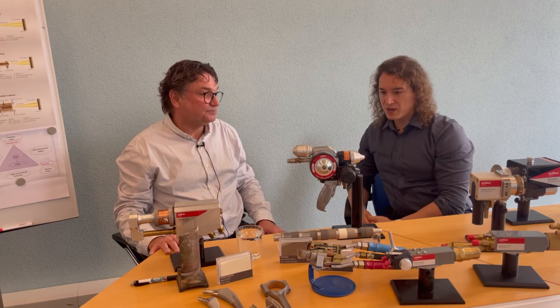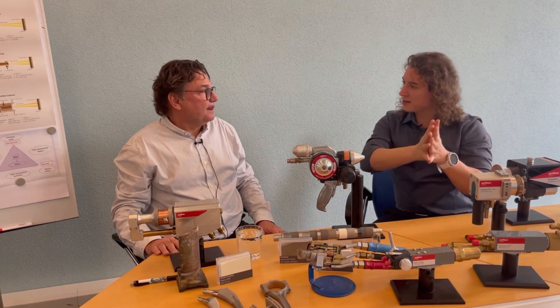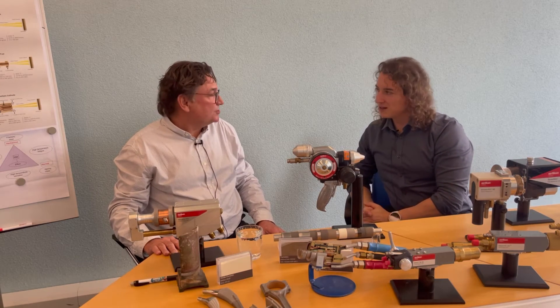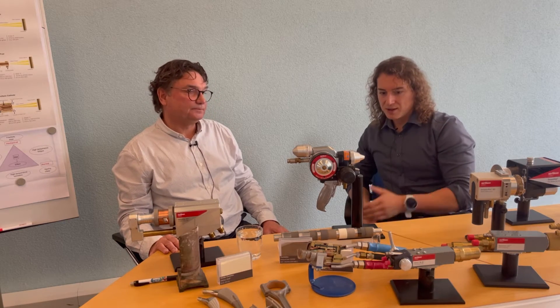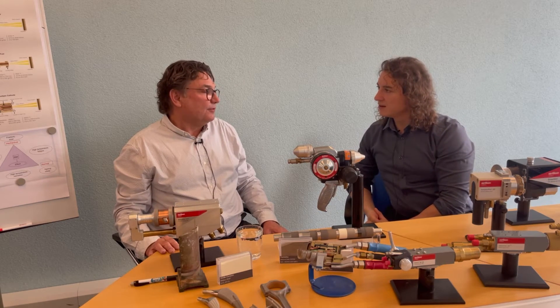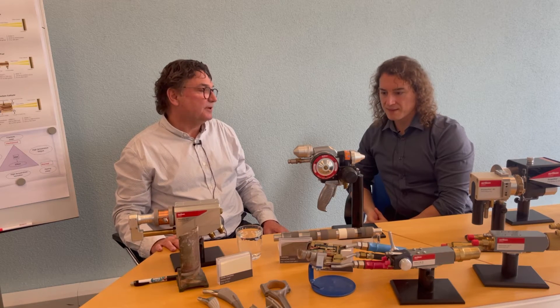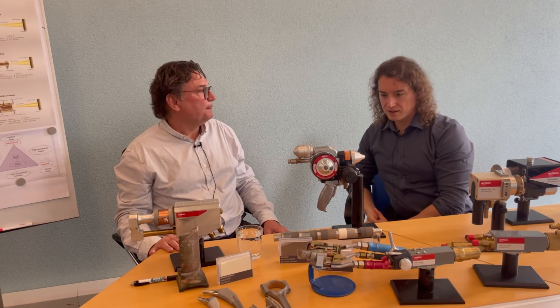The coating is built up like pancakes connecting to each other on the surface — we call it a lamellar structure. The typical coating thickness for this process is around 300 to 500 microns, and we can go up to one millimeter, though normally it's in the 300 micron range.